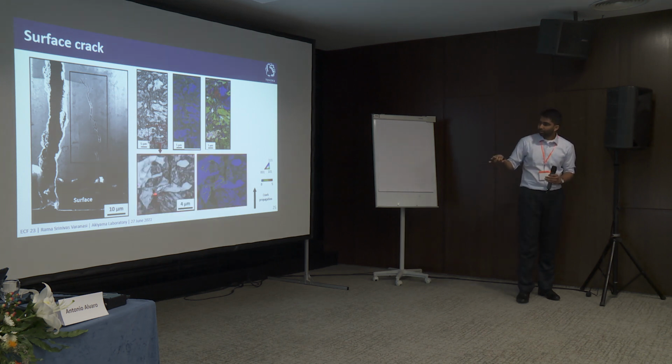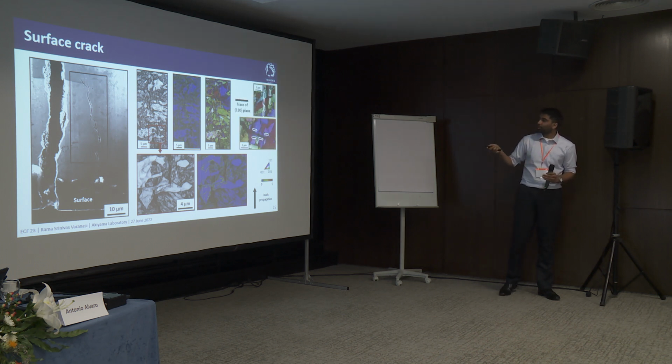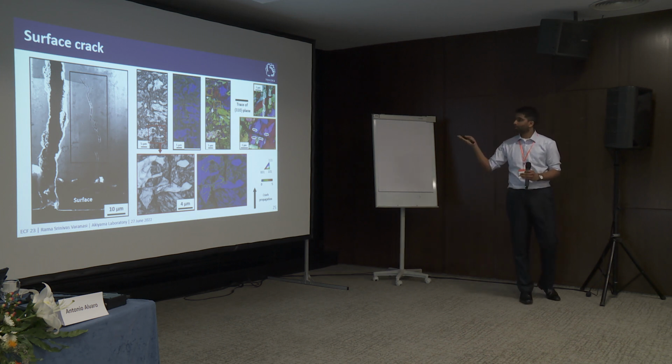Here there is a ferrite which arrests the crack, and in the EBSD map we can see that there is localized plasticity causing coalescence of the cracks. And then when we looked at martensite, we saw quasi-cleavage fracture again, with the fracture propagating along 110 planes.